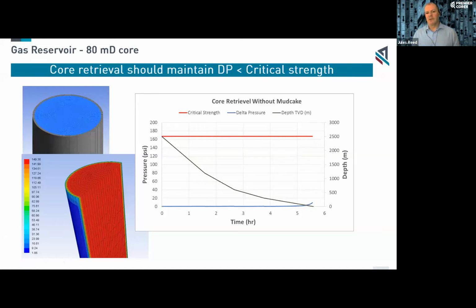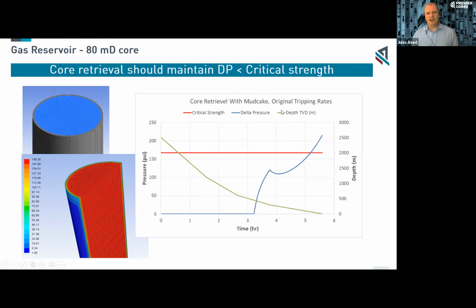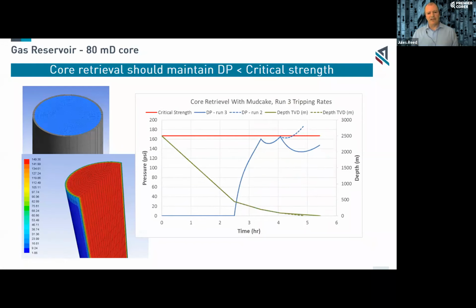But that's modeling it without the mud cake. What happens when we model it with the mud cake? Well, that same process modeled with the mud cake in place, we begin to cross the critical stress line here after about 5.5 hours or 5.25 hours. That suggests that we may begin to fracture the core. And so what we do is then begin to look at optimizing that core run.